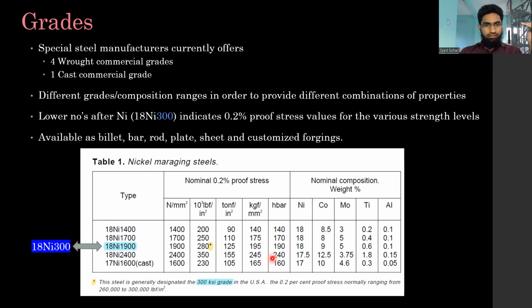But what we can see here is the composition in terms of weight, nominal composition. You have nickel, cobalt, molybdenum, as we mentioned, major share. Titanium and aluminum also have. Nickel, what we can see is almost 18%, virtually 18%, not very much. Cobalt and molybdenum and even titanium are varied in chemical composition. And these are varied to achieve different grades, isn't it? We can see that these are all different composition percentages for different grades.